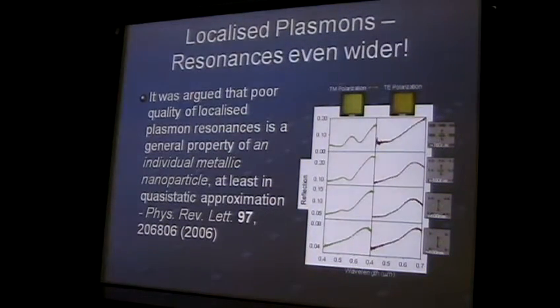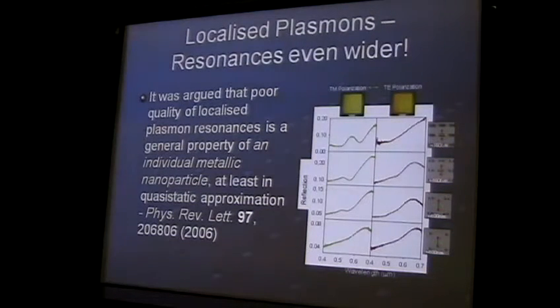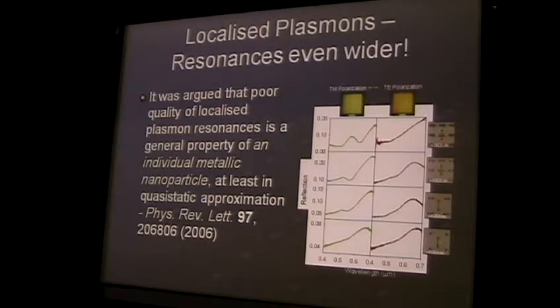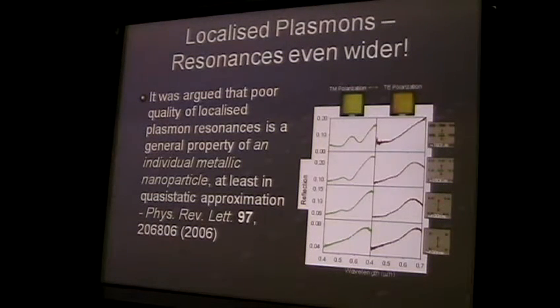It's possible to have better resonance with silver - like 15 nanometers. But silver is not a material that lives long. You can make a sample, it could live one week, and then you throw it away. As far as gold is concerned, you can make a sample and after two or three years, put it into a different situation and it will still work.